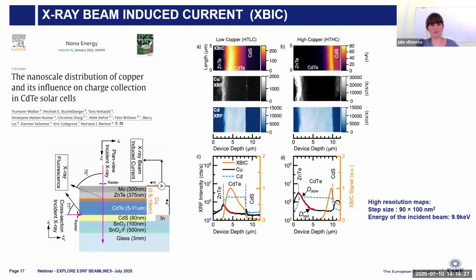As an example, here is the study of the influence of copper on charge collection in some cadmium telluride solar cells. Here you have a schematic of the multilayer of the solar cells, and the measurement was performed on the cross section. And here are the results. At the same time, you obtain the XBIC map, but also all the fluorescence maps. Here you have the copper, you have the cadmium, and by correlating those maps, you are able to look at the impact of the localization and distribution of the copper, in fact the incorporation of the copper in the layer, on the variation and the transition of the maximal charge collection in this kind of sample.